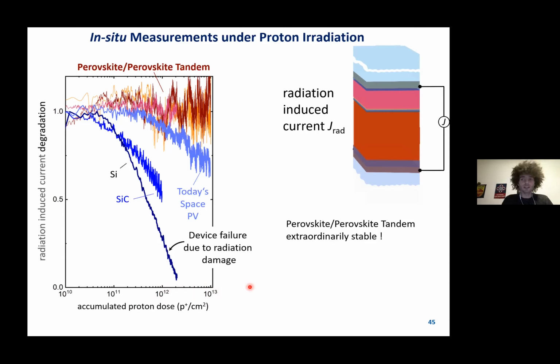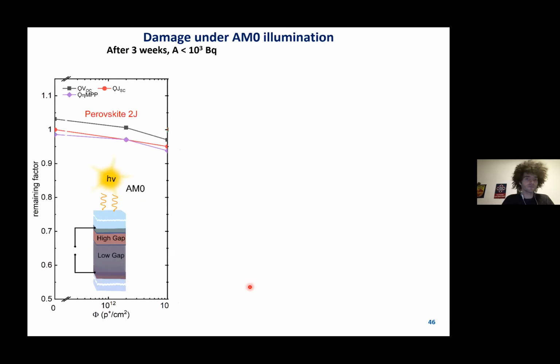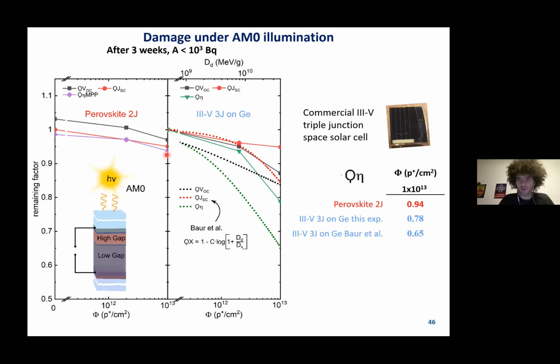All right. So they look very promising when we look at the radiation-induced current, and I, of course, also characterize them after. I'm showing now the remaining factor of VOC, the JSC, and the efficiency at maximum power point of that perovskite tandem as a function of proton fluence under AM0. And you can see it degrades to around 94% of its initial efficiency. If you compare this to a standard III-V triple junction as it is used right now, this is very stable.